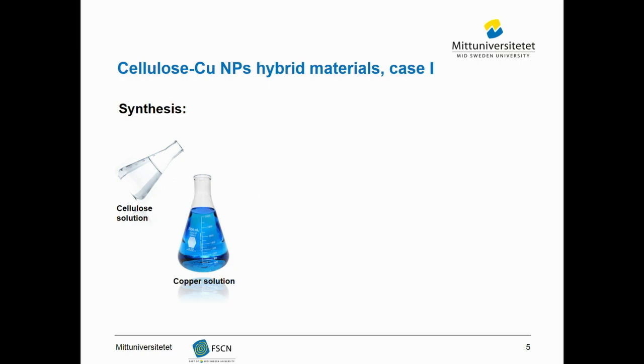Here are some examples of our work. In our group, we developed a synthetic approach to produce cellulose–copper nanoparticle hybrid material. We use cellulose solution as a source of cellulose and mix it into a copper solution as a source of copper. Then by adding a proper reducing agent, we can synthesize copper nanoparticles decorating the regenerated cellulose inside the solution. The whole synthetic procedure is quite fast and reproducible — it can be finished in less than 10 minutes — and the final hybrid material can be easily separated from solvent by simple vacuum filtration.